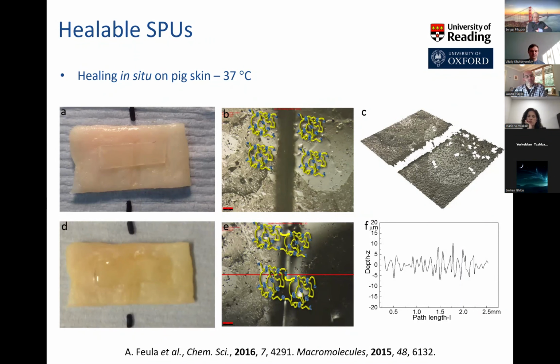There's a little bit of creep with our material as well, but you can see in image B and E of the damage zone where the valley has simply filled up, and that's also indicated by the profilometry plot, where we've run the profilometer across the surface, and we can't detect a valley of any great note.